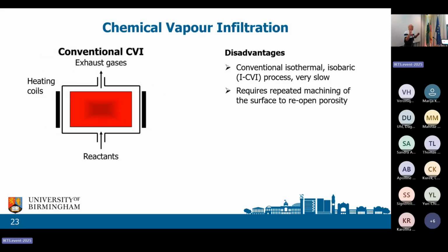The disadvantage. You knew there was a disadvantage coming. There's always a disadvantage. It is slow. I mean, seriously slow. When you heat anything in a furnace, what's the hottest bit? The outside. So you heat really slowly. You heat to 1,000 degrees centigrade at something like 1 degree heating rate per minute. So that's 1,000 minutes to get to temperature. Even then, you've got temperature gradients. And temperature gradients mean that where does your deposition happen? It happens on the outside of the body.